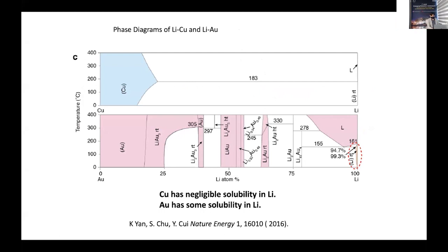And this is really telling us once lithium comes in, deposits onto gold, it alloys with gold, first alloy phase, second alloy phase, and then lithium continues coming in, it will have the ability to dissolve gold away. However, lithium cannot dissolve copper away. And once lithium dissolves gold away, lithium makes gold more look like lithium before lithium deposition happening. There's no overpotential for the case of gold.